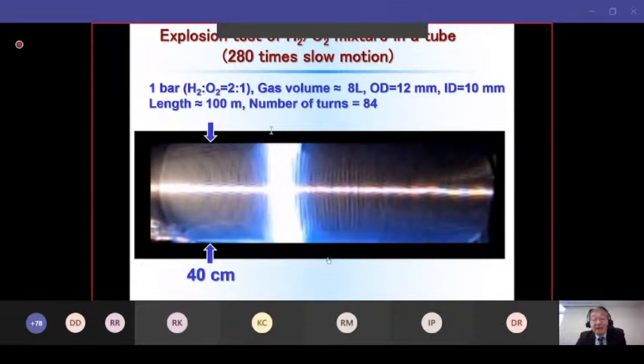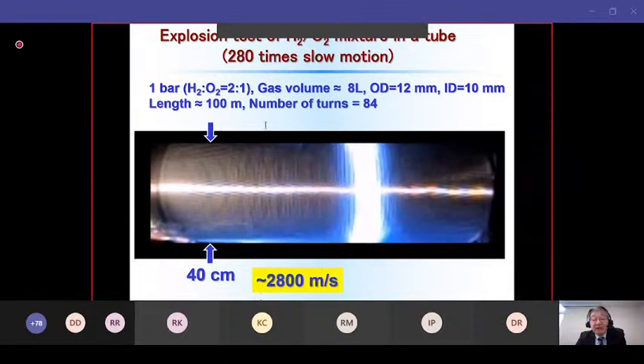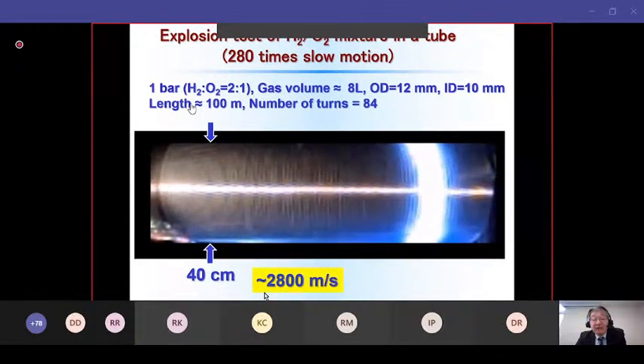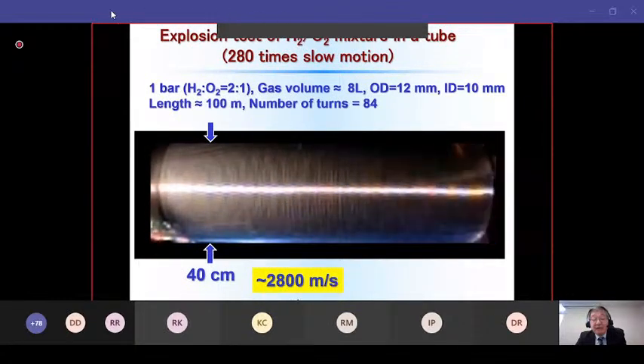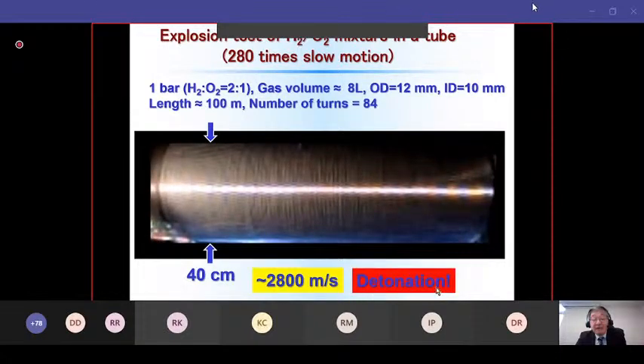So from this video, we can evaluate that this explosion proceeds at about 2,800 meters per second. That is much faster than the velocity of sound, so it is a so-called detonation. However, we observed almost no damage. We can carry out the same experiment many times.